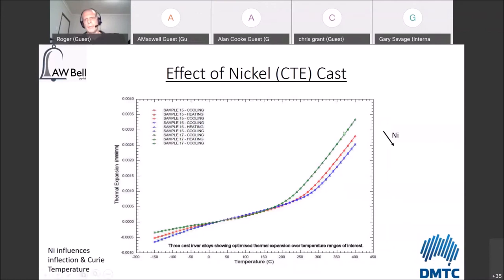So as we go up in nickel content, we're going from the green curve to the red curve to the blue curve, which is completely in line with what we saw for the wrought material. Now, the green curve is very, very similar to alloy 1. It is actually in specification for the alloy 1 that I showed you earlier, the GX3 nickel 36 material, and the blue one is not that different from the Boeing specification. So you see exactly the same trend. Able to prove out that yes, nickel does influence the curve in this way.